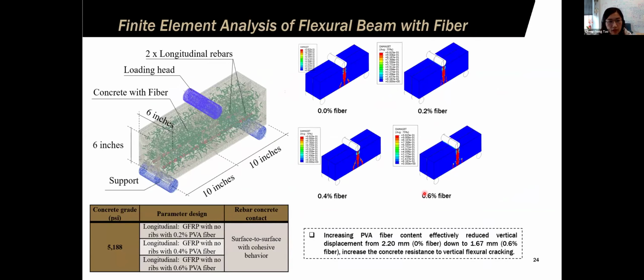Also, we consider the effect of fibers in the concrete materials by changing different PVA fiber content in finite element analysis. With the increase of PVA fiber content, it reduces the vertical displacement and increases the concrete resistance to vertical flexural cracking.